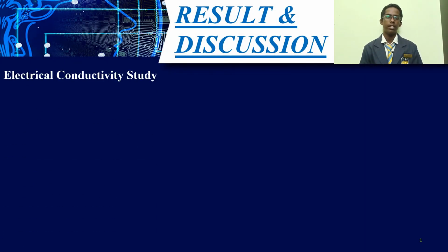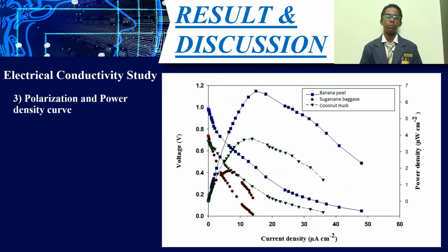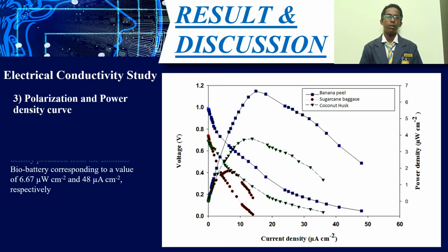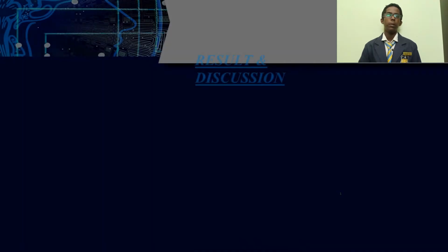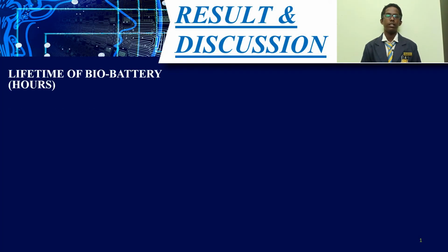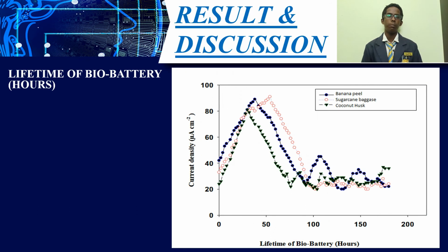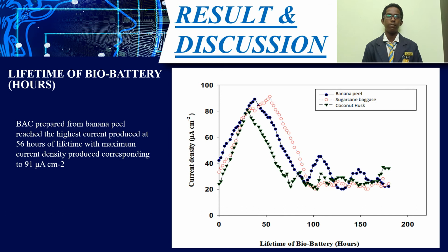In the last test, we found that the highest power density and current density produced from the BSE biobattery corresponding to a value of 6.67 microwatt per centimeter square and 48 microampere per centimeter square respectively. Based on our lifetime biobattery test, BSE prepared from banana peel reached the highest current produced at 56 hours of lifetime with maximum current density produced corresponding at 91 microampere per centimeter square.